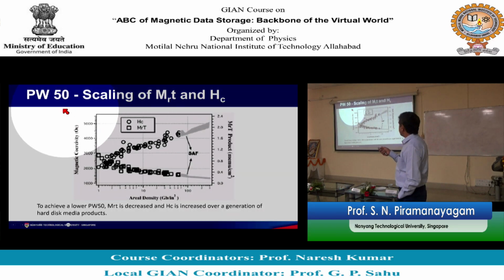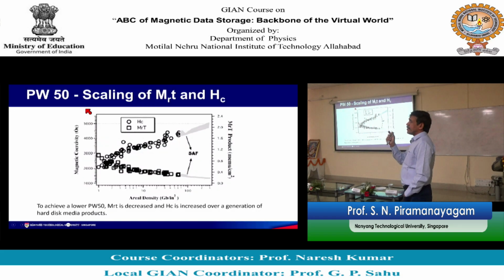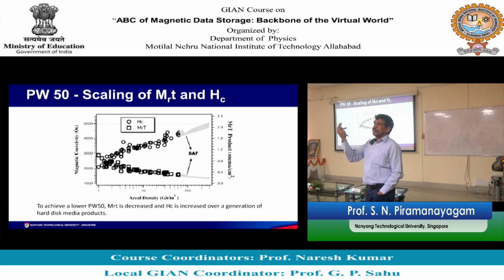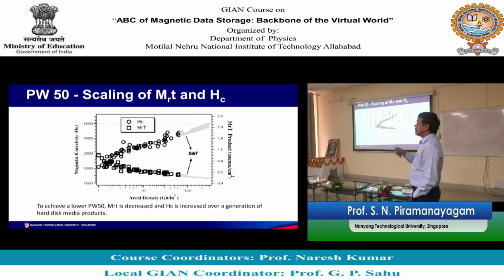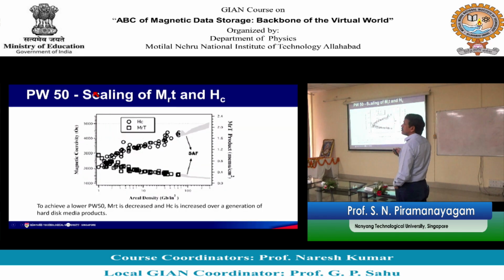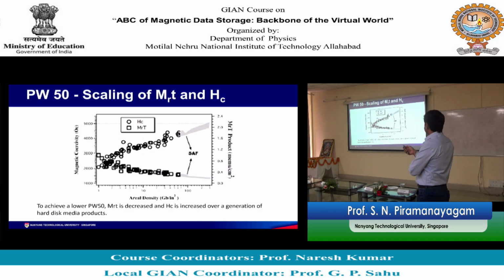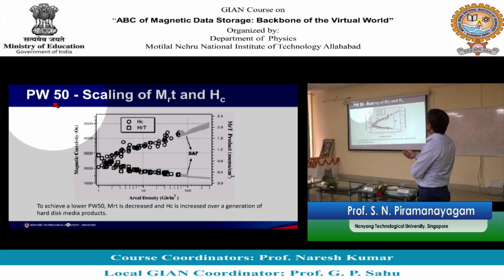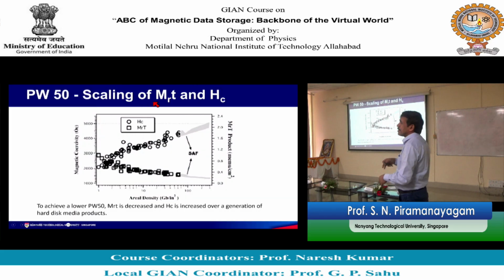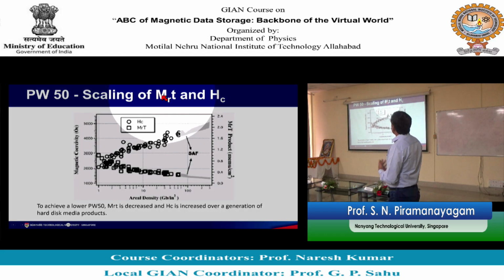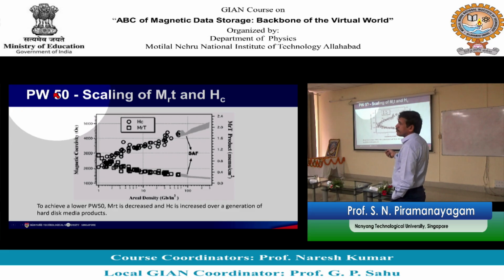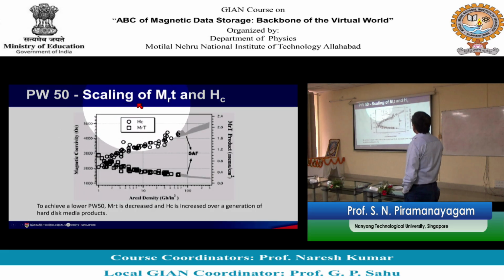And yesterday we did not discuss this one, PW50. Basically, PW50 is the width of the pulse. So, you can imagine that to be the tip of the pen. So, you want a smaller tip for writing more data, right. So, if PW50 is large, then you cannot pack information at close distances. So, we need to reduce the PW50, and PW50 is proportional to MRT. So, that is why I told you cannot increase the MRT too much. If you increase the product of remnant magnetization and thickness, you are going to increase PW50, which is not good. So, you want to reduce this, and PW50 is inversely proportional to coercivity. So, if coercivity is large, PW50 is small. So, we want to decrease MRT, increase coercivity.